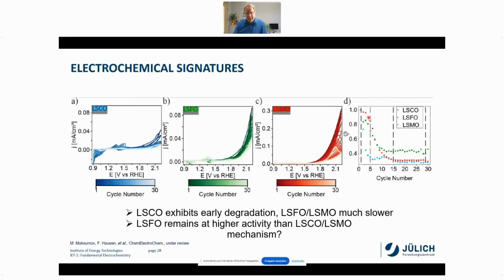And if you compare how quickly, then you see that here in this figure D, for the blue material, which is the LSCO material, we have a direct, quick degradation or an early degradation, and it stabilizes at a really low level of the current density, whereas for the LSFO, so with the iron material, we have a rather slow decay and degradation of the material, and the decay stays at a higher current density. So in principle, the material is more active at higher cycle numbers.